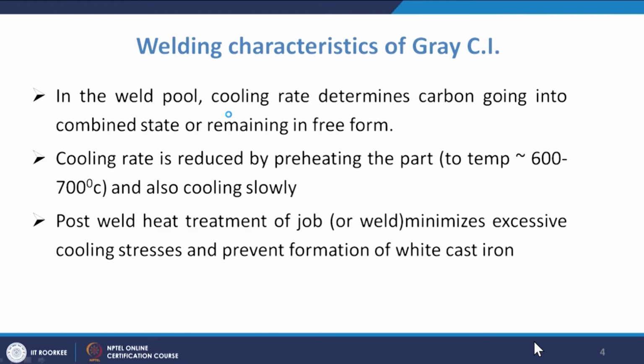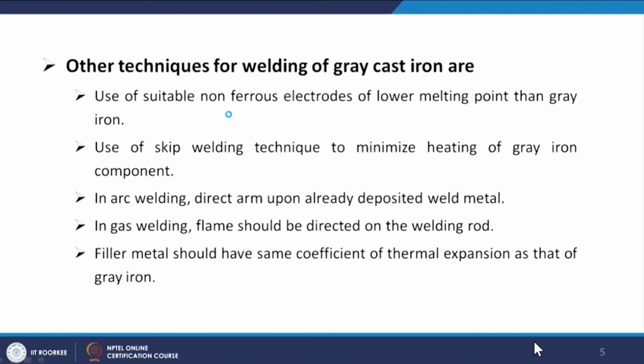Post-weld heat treatment of the job minimizes the excessive cooling stresses and prevents the formation of white cast iron. In grey cast iron, we have the graphitic flakes. So if we do faster cooling, it will convert into white cast iron.